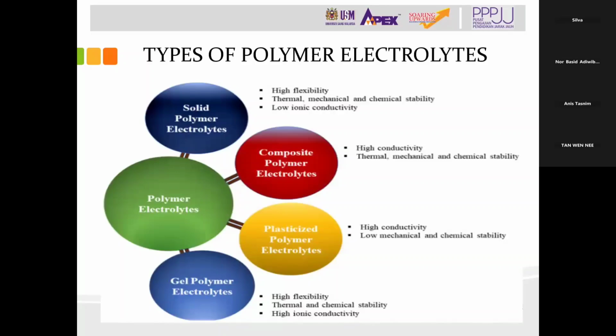How about plasticized polymer electrolyte? In plasticized polymer electrolyte, we have high conductivity and low mechanical and chemical stability. Plasticized polymer electrolytes are formed by dissolving low molecular weight compounds such as ethylene carbonate, propylene carbonate, and polyethylene glycol. All of these we call plasticizers. This plasticizer reduces the inter- and intramolecular interaction between the polymer chains, reduces the Tg and crystallinity of the polymer chains, and enhances the salt dissociation ability.